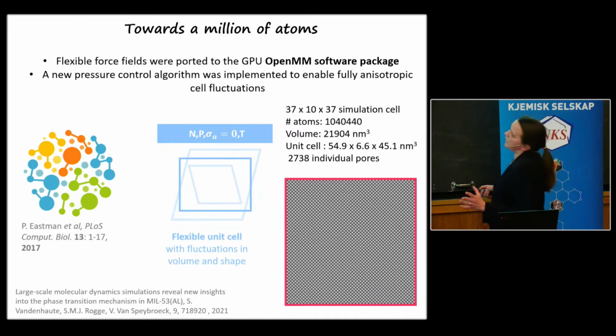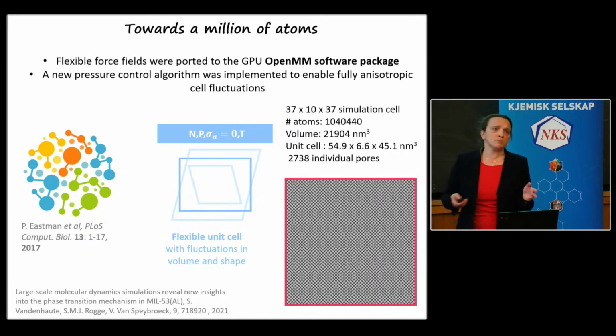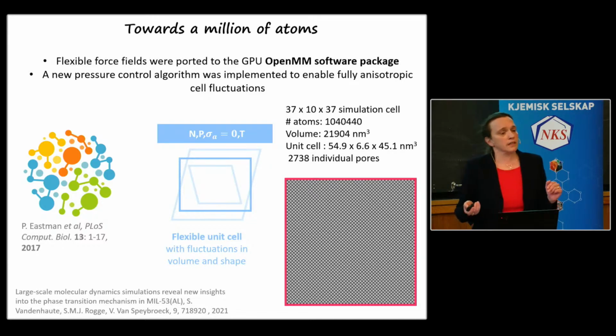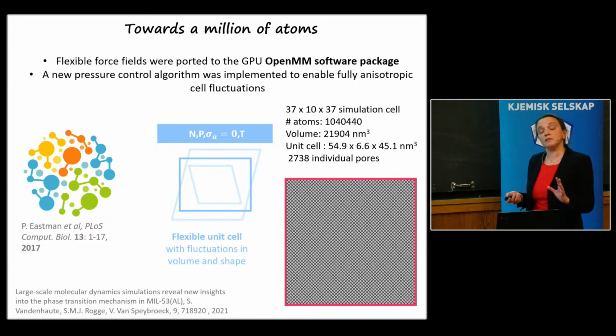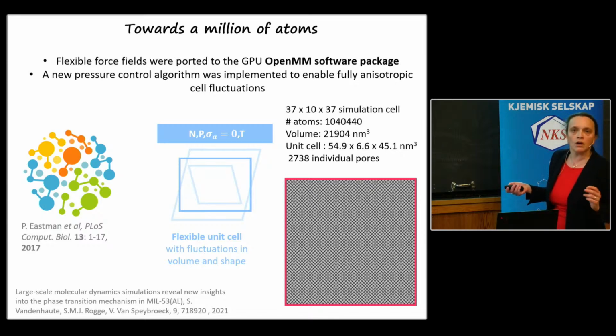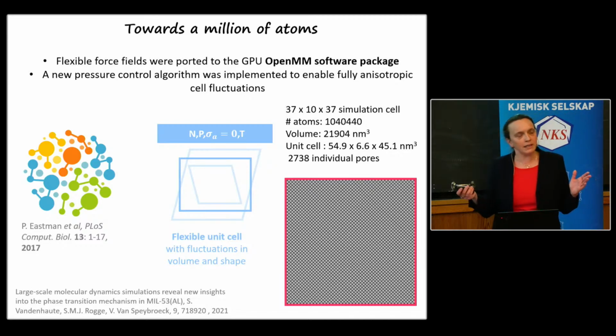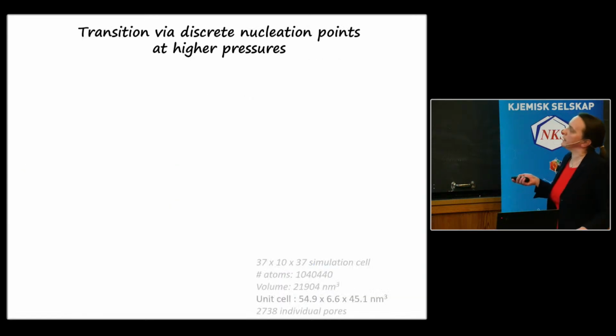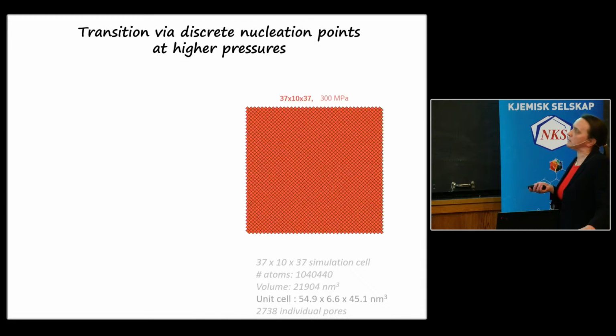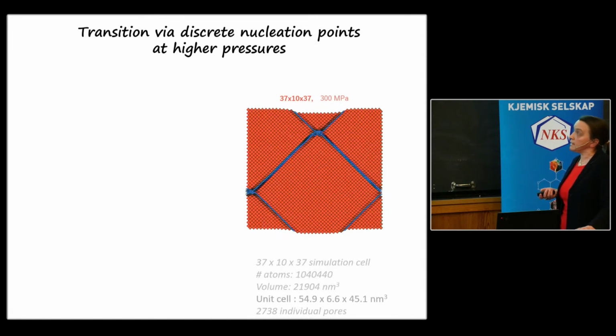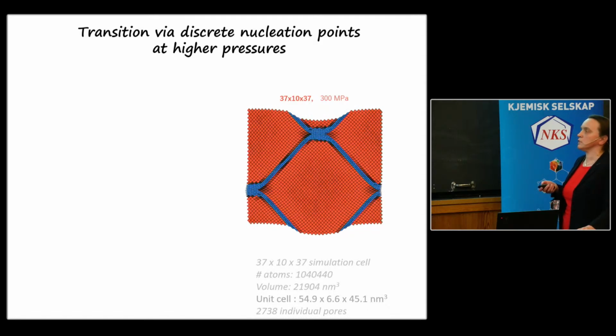Then we were not really satisfied. We said 10,000 is good, but maybe we have to go to bigger crystal sizes. And so we wanted to go to 1 million atoms. For that to happen, we used very efficient techniques also from the biochemistry field, biosimulations. We are of course used to doing very large simulations. So we went to 1 million atoms, and then we look again at the movie, and it seems that even then you can induce other transition mechanisms.